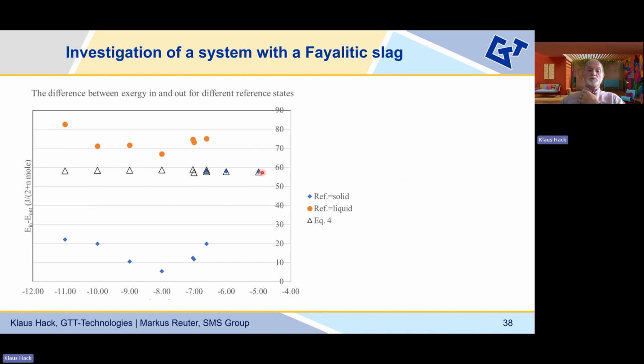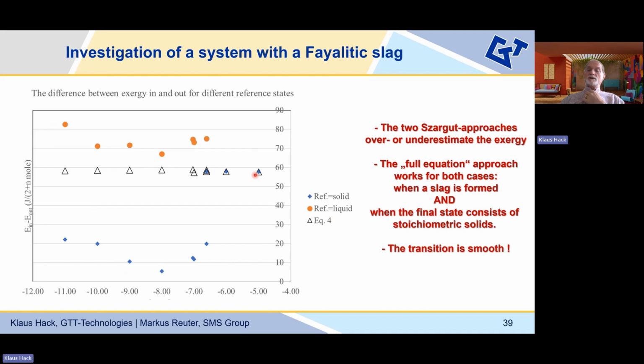And for us, that is really now the proof. Forget about those reference state discussions, which follow from Szargut's definition. Simply use the general formula all the time, and then you have all the time a unique number which tells you what the exergy dissipation is. So the two Szarguts overestimate or underestimate, and of course there is this transition between the slag range and the solid range, and now that is a smooth transition, as you can see from the triangles, instead of having a jump when we base the calculations on the two possibilities of Szargut.